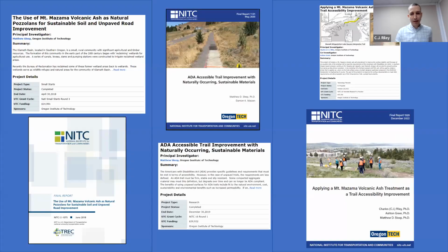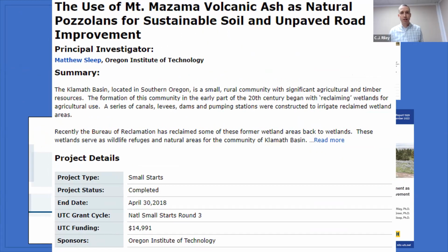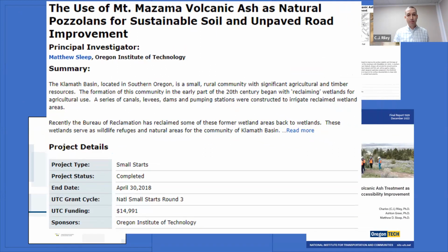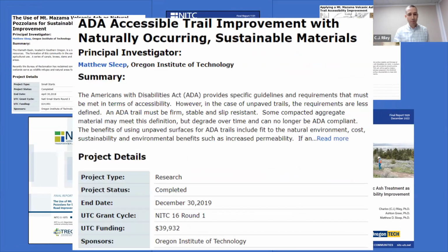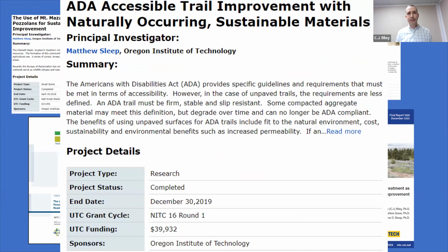Thanks, Ashton. So here we have 3 different studies. The first one on the left was a preliminary study that attempted to use the Mazama ash as an improvement for unpaved roads, in particular levees in the area that are composed of poor soils and often have roadways across them. A second study by Matthew Sleep, one of our former colleagues, tried to focus in on accessibility improvements and really started us thinking along these lines. There were thousands of mortar cubes cast and broken in this study that really gave us a good idea of how this ash performs when it's combined with different cementitious materials like Portland cement, like lime, and other products.